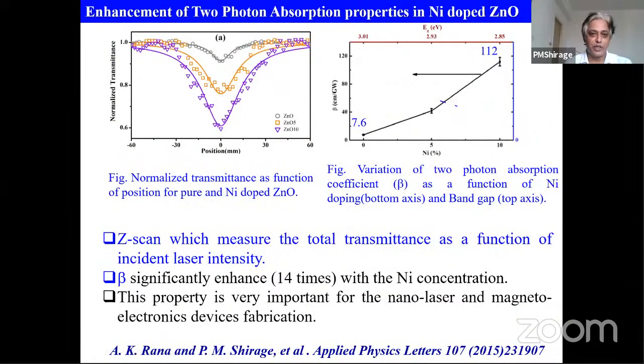Another important piece of information that we measured is the 2-photon absorption spectroscopy of this material, nickel doped zinc oxide. We measured the absorption with the Z-scan, basically the transmission of light through the material and how much it will transmit. That gives important information about the absorption coefficient of that particular material. In the case of pure zinc oxide, this beta is 7.6, and when we replace zinc with 10% nickel, beta is 112. It means a large increase in beta, and that is very good for lasing applications. So this nickel doped zinc oxide is very good for lasing applications.